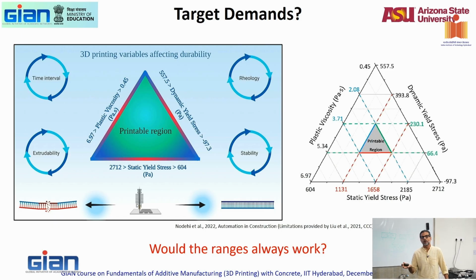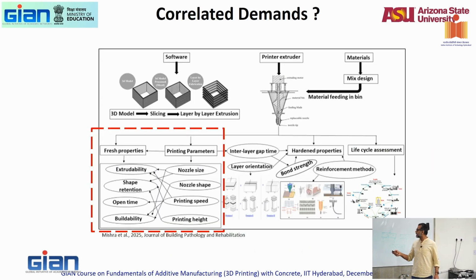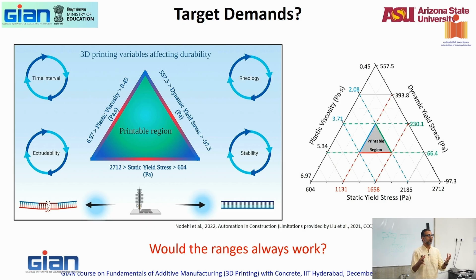No. But like every good optimization, you should get 2 of the 3 correct. One of the 3 probably won't work. None of the 3 absolutely is a disaster. But at least 2 of the 3 parameters that you want, you should be able to pick which ones you want. So there's a very, very simple conceptual diagram to show, because right now, you know only about yield stress and viscosity, correct? You know static yield stress, dynamic yield stress, viscosity. What is that printable region in which this works? And this will in turn help you find the mix that satisfies these given criteria.